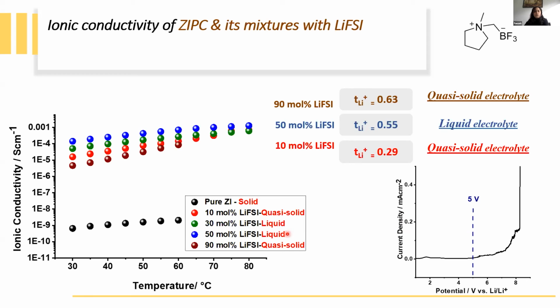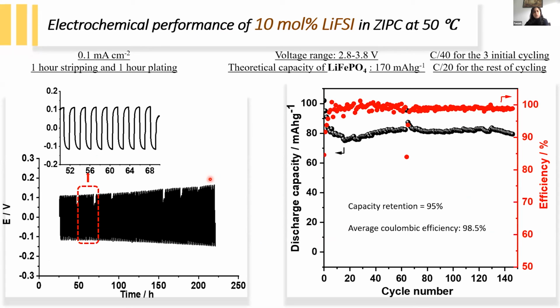So based on all these results, we studied the electrochemical performance of the materials. As an example, here I'm talking about a low concentration lithium FSI, which in a lithium symmetrical cell showed that the stripping and plating of lithium is very stable. And also, in collaboration with Battery Hub, we made a full cell based on a lithium metal anode and an LFP cathode, which is a very stable and safe cathode material for lithium batteries.